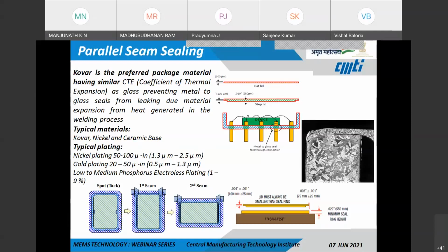And for rectangular or square packages, the weld is accomplished in 3 phases. As we see here, the first phase is spot or tacking, wherein only one weld is generated, followed by the first seam, wherein the first run is done on one axis, and then the package is indexed, and the second run is done. So here we see a good weld between the lip and the package body. This is considered to be a very good weld.